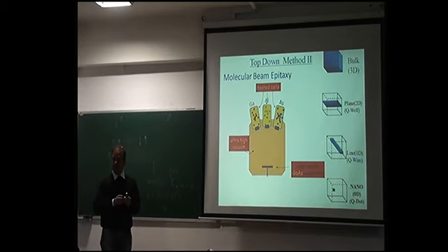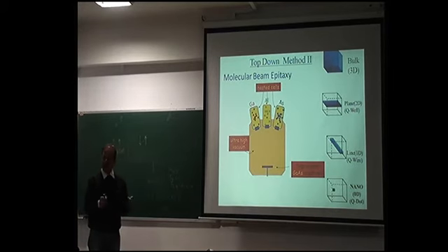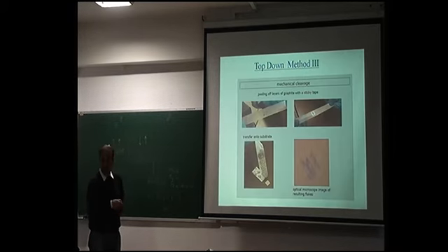If you have ultra-high vacuum, the chamber is typically about 1 meter, but at 10 to the minus 11 torr, the mean free path is 10 meters for most of these atoms. So there is no problem. You have to make sure that when the atom is coming from here to here, it is not diverted because of scattering. That's all you have to take care of. And the background pressure is decided by this fact. So this is another way of making top-down structures. You can get, of course, 2D, 1D, and 0D systems by this method. I'll come back to this method a little bit more.